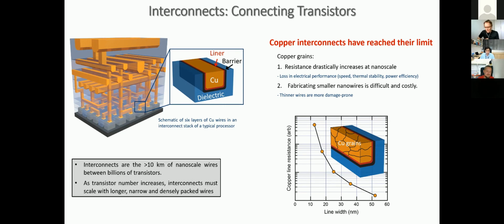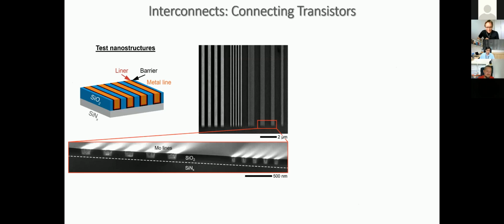So what do we do? We look at different metals: moly, tungsten, ruthenium. This is a typical test structure of ours. These are metal lines fabricated on a silicon nitride membrane, with different scales going all the way down to about 25 nanometers. This is molybdenum lines embedded into the membrane, and we want to understand what happens when we heat them. Can we grow the grain size? Can you control the crystallinity by annealing it, for example under a reducing atmosphere, because a reducing atmosphere removes the oxide between the grain boundaries?